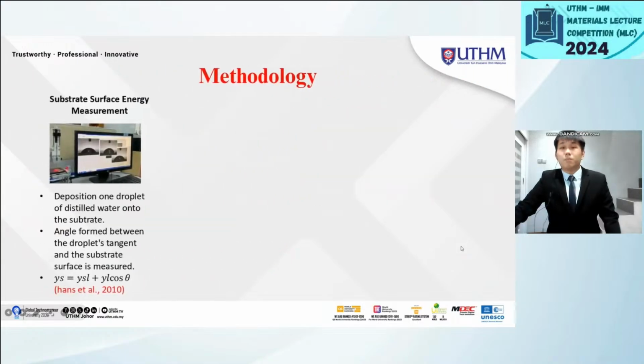The first step in the methodology will be measuring substrate surface energy. Nine selected substrates will undergo this process. A droplet of distilled water will be deposited on each substrate, and the contact angle will be measured. Using Young's equation, the surface energy value will be calculated.